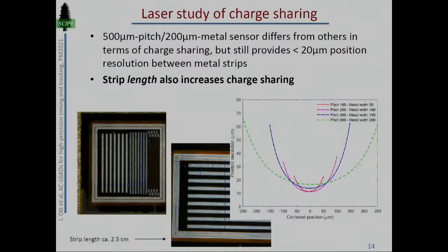Something similar can also be done with the laser. These previous were all test beam results, but we can also work with the laser in the laboratory. These are different individuals now, newer production AC LGAD strips. Again, we get down to around 10 micrometers of position resolution, but this other sample here, the one in green, behaves quite differently from the others. That was rather interesting to see because the main difference here is the strip length.